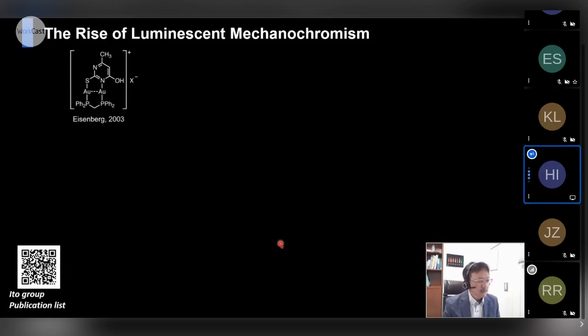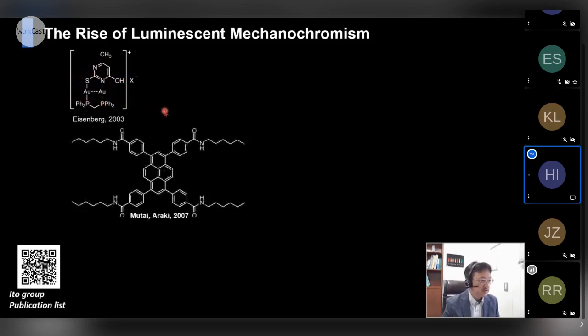And for the case of this gold complex, Professor Eisenberg had already reported that this gold complex shows a luminescence intensity change under mechanical stress on the crystal compounds of these molecules. And at almost the same time as our publication, Professor Mutai and Araki at Tokyo University reported that this pyrene-based organic compound also shows a very similar luminescent mechanochromism. They reported these results in JACS, and maybe their paper and our paper can trigger this field of research.